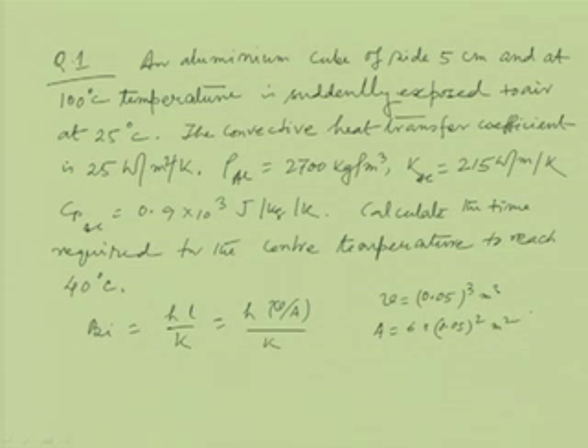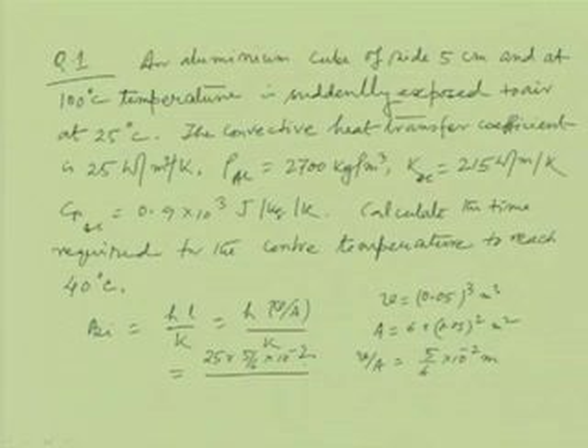Okay. So we will get V by A, and if we do the calculations, it is equal to 5 by 6 into 10 to the power minus 2 meter. And then what is the value of Biot number? If we do the calculations, it is equal to 25 into 5 by 6 into 10 to the power minus 2 divided by k, which for aluminum is 215. The Biot number is a number, so it is unitless, and this value is equal to 0.00097, which is much less than 0.1.